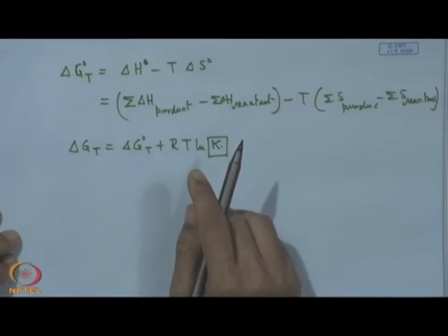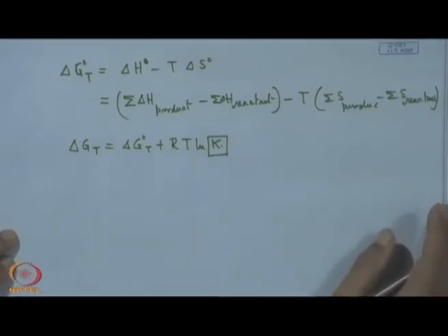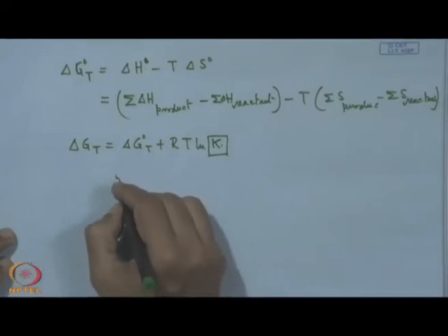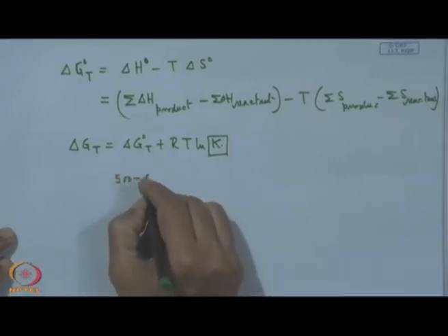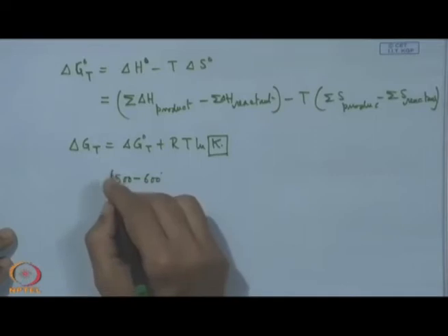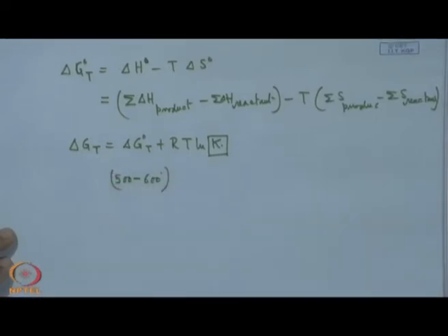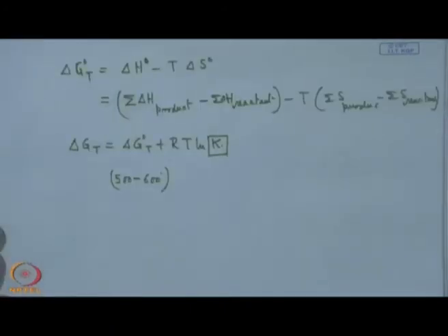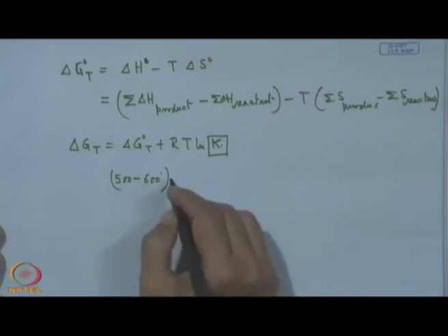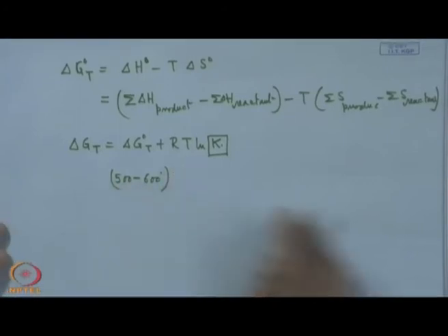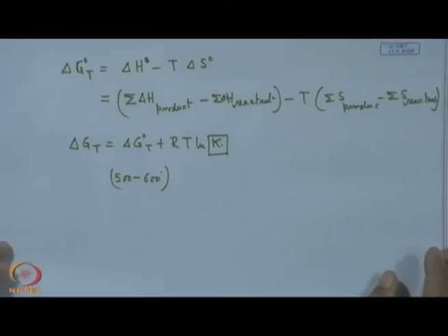As per the documentation, it is reported that around 500 to 600 all these reactions which are explained here by these 4 equations can take place within this temperature of 500 to 600, and which will be not only of academic interest, but will be of theoretical or industrial importance.